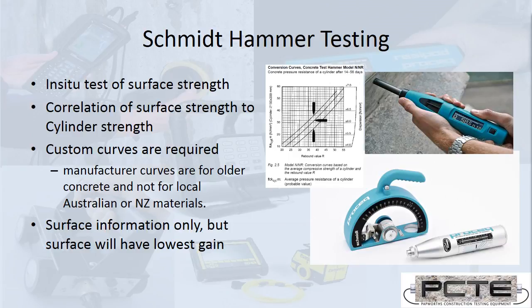We take this measure of energy returned and, based upon compressive strength tests, relate it back to a concrete strength. Schmidt hammers are used for testing new and old concrete, and often there will be a curve printed on the side of a Schmidt hammer, or the Silverschmidt models will report MPa from a number of built-in curves. Those curves are not really suitable for early age strength. We already don't have a relationship to a particular mix, and even more than that, we have a relationship to materials that are not Australian. Those are very often a European test of older concrete. So it's really critical to build your own curve if you're going to be using a Schmidt hammer for early age strength measurement out on site.